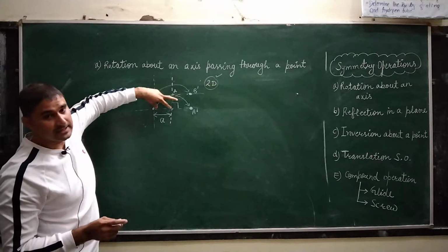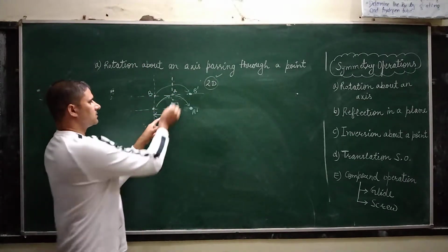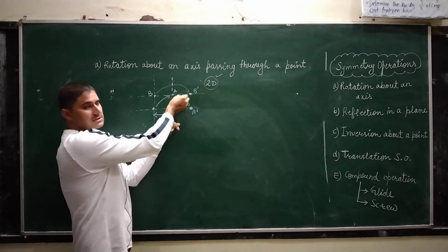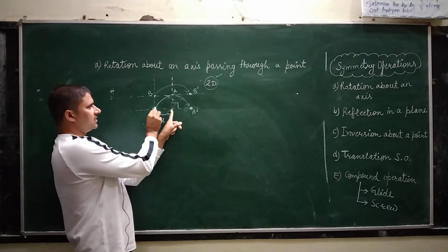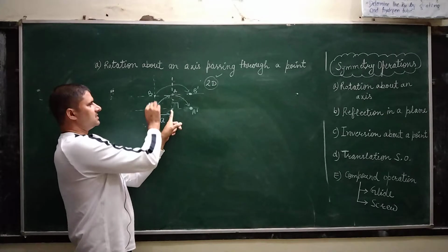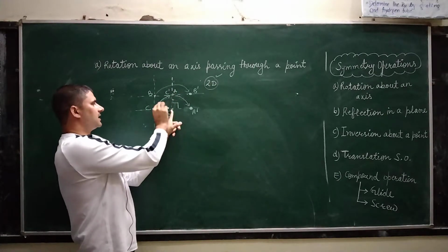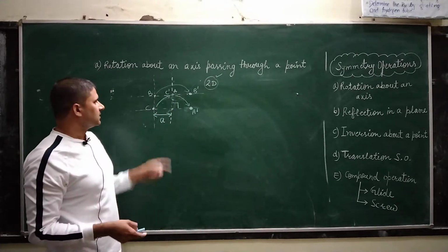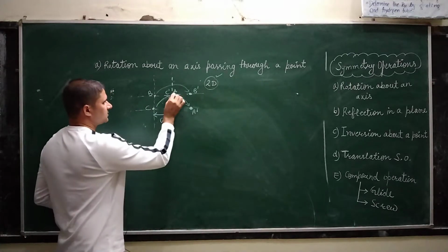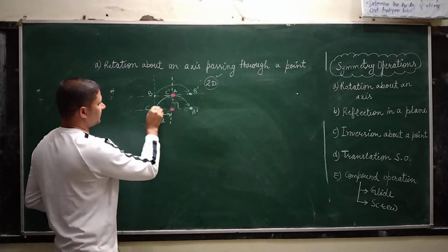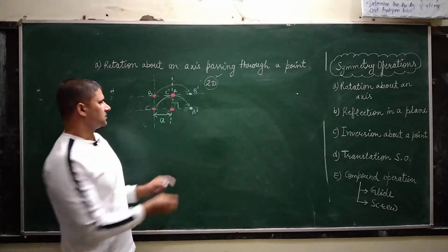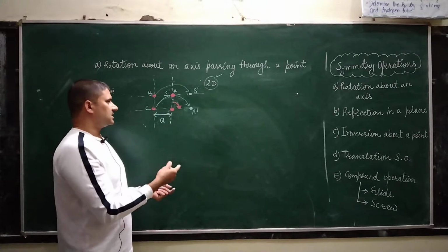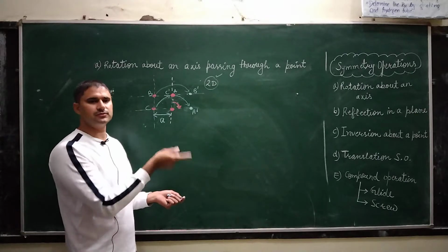Now after rotation you will see this is again at a distance, let's see it in depth. Let the arrangement of particles be at a distance of A in both directions. So this distance is A, here this distance is A, this distance is root 2 A, and after rotation this distance is again root 2 A. So if this particle, let this be C particle, goes to the position of C dash after rotation, then before rotation it was at a distance A and now it is again at a distance of A. So I can say that if this kind of arrangement of particles is present, and if I rotate this by 90 degree in clockwise or anti-clockwise direction, then the symmetry of the crystal structure remains the same. It will be the same as it was before the operation, okay class.